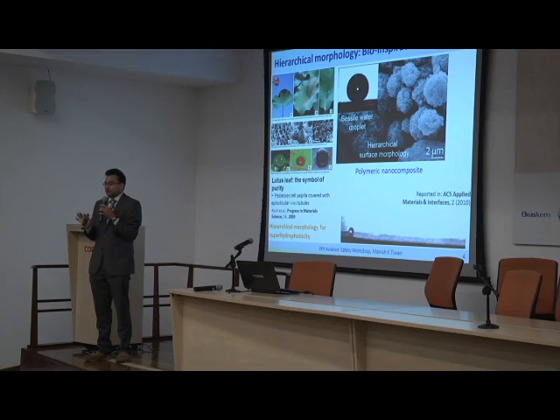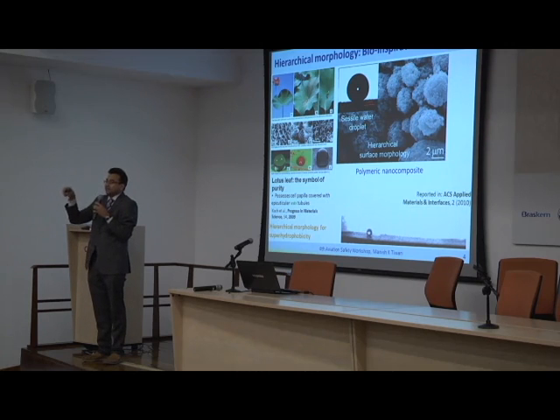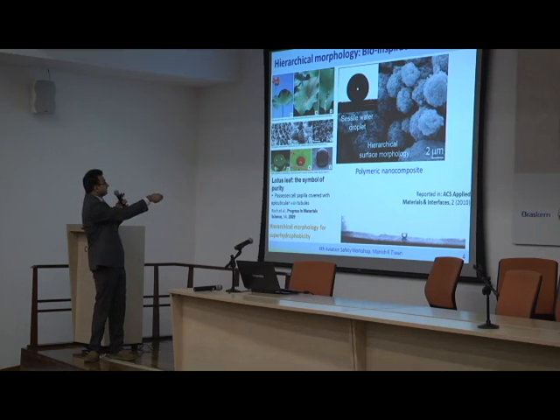And the reason for that is its extreme hydrophobicity. Now, just to give you, let's say, a flat-out truth, of all the material that we have been able to synthesize as of today, if you take the most hydrophobic material that you can think of, Teflon, perfluorocarbon, and so on and so forth, and you make a smooth surface out of it, and you place a water droplet on top, and you try to measure the angle of the water droplet, which is what we call contact angle, you'll get a contact angle of about 130 degrees. This thing has a contact angle of 150 easy.